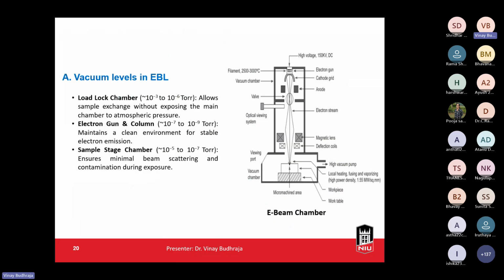Vacuum levels which are being used in EBL. EBL is a short form of electron beam lithography. One level of vacuum from 10 power minus 3 to 10 power minus 6 torr is being required in the load lock chamber. The load lock chamber is where the samples are being kept. It allows sample exchange without exposing the main chamber to atmospheric pressure.